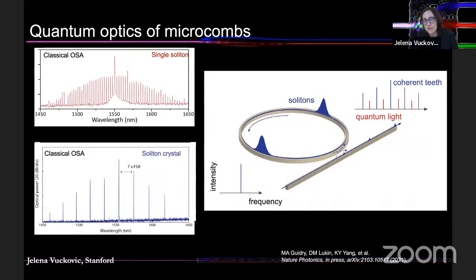Recently, inspired by this nonlinearity, we also investigated nonlinear optical effects, and we're continuing to work in this direction, also in collaboration with Scott Papp's team and collaborators at NIST and elsewhere. This is very exciting for us because by fabricating these new, high quality structures, we've been able to observe single soliton microcombs with comparable thresholds to those in other materials, including silicon nitride and tantala that NIST is pursuing. We've also observed soliton crystals, with excitation of particular lines in these soliton combs.